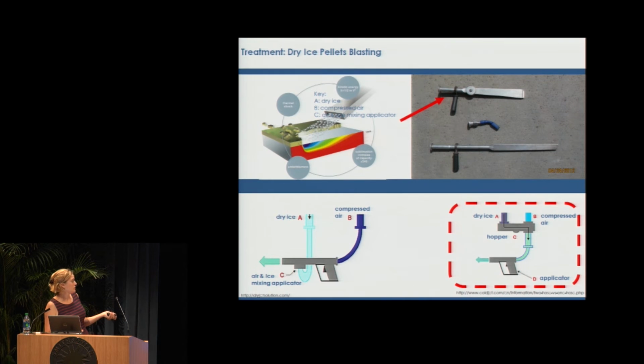But the advantage of the single hose is that you can have a much longer hose, which was necessary for us because we had to go around the sculpture. So you also have to think about the necessity of cleaning and being able to go around it. A second advantage is that you can blow upward with your nozzle. With the double hose, you cannot blow upward with your nozzle. For us, because we had to go under the sculpture, it was also pretty important. But if you have more questions about these 2, I can always explain it later.